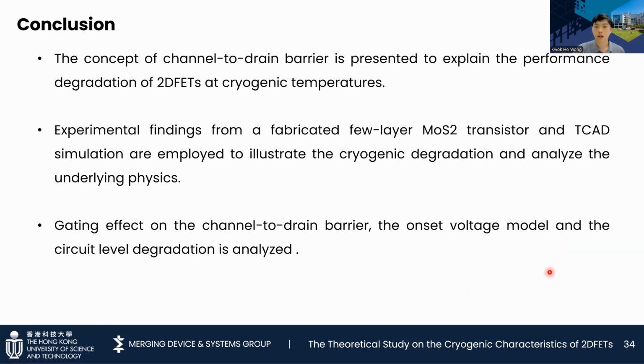In conclusion, in this work, I explained the performance degradations of 2DFETs at cryogenic temperatures by presenting the concept of the channel-to-drain barrier. Furthermore, experimental findings from a fabricated few-layer MoS2 transistor and TCAD simulations are employed to illustrate the cryogenic degradations and analyze the underlying physics. Furthermore, gating effects on the drain barriers, the onset voltage model, and circuit-level degradation are also analyzed.